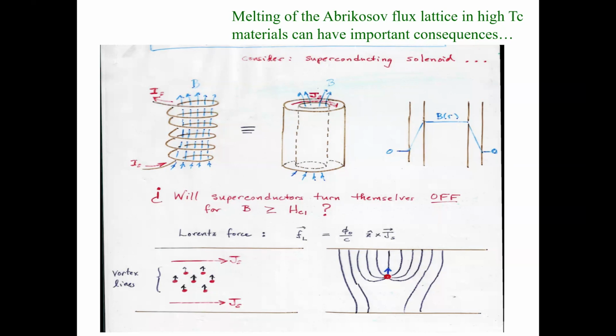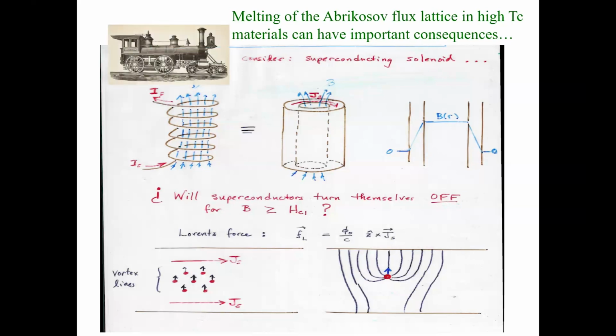But if they are able to move, it's a little bit like a plastic crystal. If you take a very soft wire, a wire made of tin or even an ordinary coat hanger, it bends and moves because dislocation lines are moving through that object and allowing plastic deformation. That happens even more easily with these vortex lines. And so why would you care about that if you were trying to make an application? Well, suppose you were trying to levitate a train. Japan, so maybe the bullet train, we have floating on the rails with solenoids. This was a dream 25 years ago.